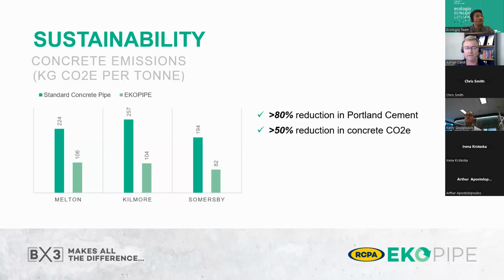And what it shows, as you can see on the graphs there, is a pretty substantial reduction in concrete emissions, in embodied carbon per tonne of concrete itself. That's achieved through a greater than 80% reduction in Portland cement, and it depends on the location. There's a bit of variability there, and we are talking about the concrete that's actually being made in those plants. So these are not abstract numbers, they're real numbers, but it does translate to a greater than 50% reduction in the CO2e for the concrete itself.